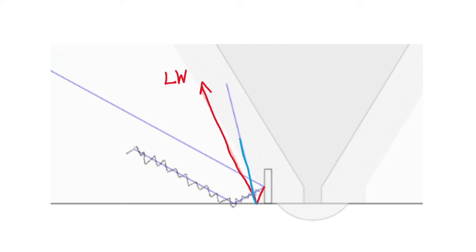But at the back wall, that long wave mode converts back into a shear wave. With photoelastic visualization, we can see both these mode-converted waves coming up from the notch. At the top there's the long wave traveling faster, and you can also see the different wavelength — the distance between the dark and light parts — compared to the shear wave.